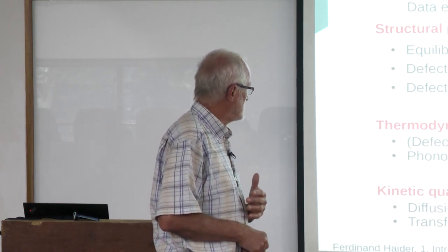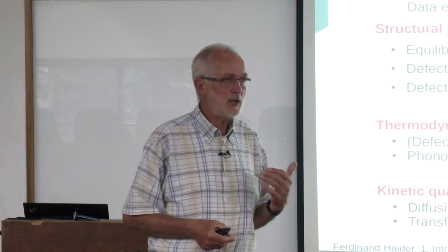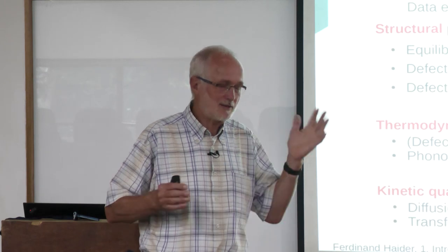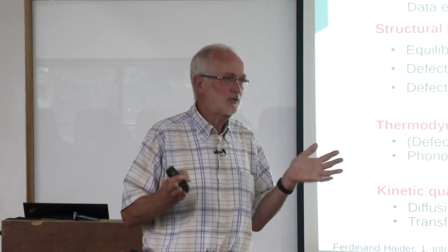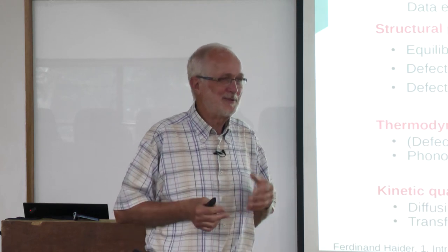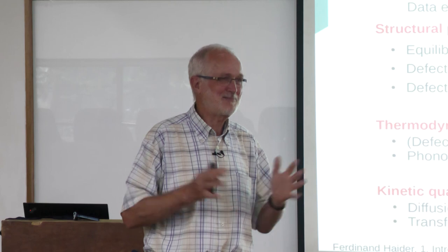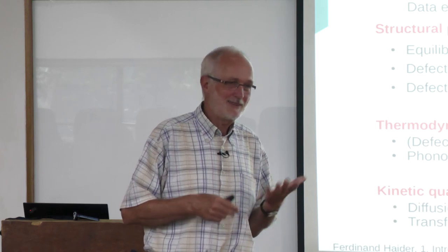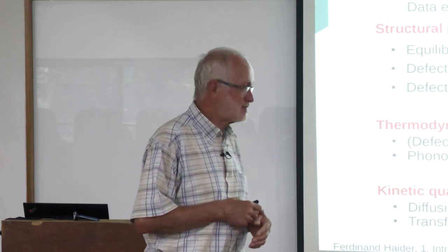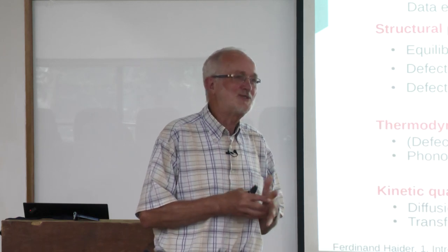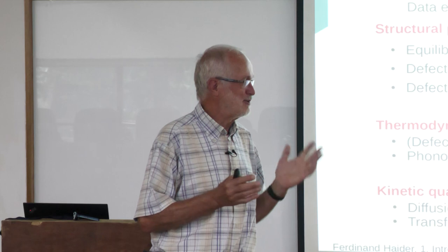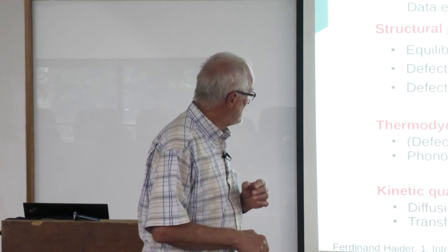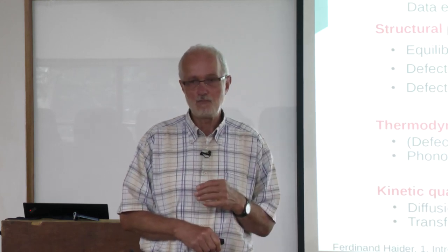Another important thing you get from MD are vibrational properties. Even at zero Kelvin, atoms vibrate. That's a quantum mechanical phenomenon. But normally, we are not interested in these very low temperatures. At normal temperatures, like here in the room, you have vibration of the atoms. In the language of quantum mechanics, these are phonons. These phonons have what we call a phonon spectrum. They have certain energies, certain wavelengths. So one can easily compute phonon spectra using molecular dynamics.